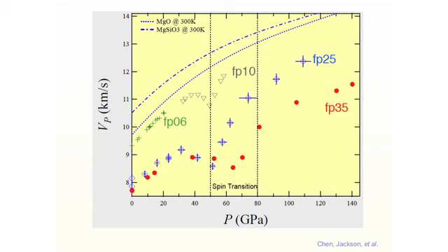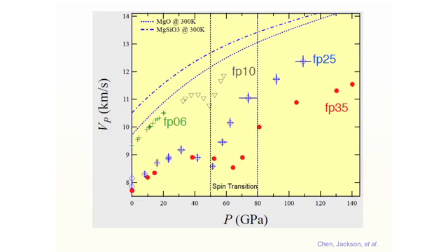And this region right here is due to that spin crossover. Those outer D electrons are pairing and causing this behavior that wouldn't have been predicted if we had stopped, which had happened about 10 years ago at about 20 or 30 GPa.